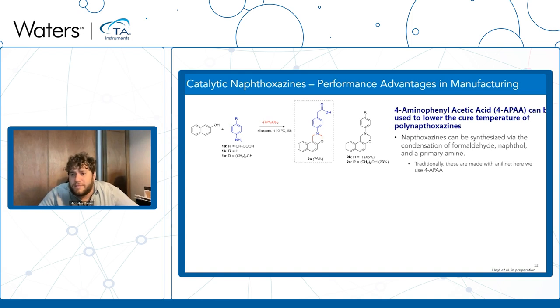And we can make robust materials. The problem with naphthoxazine resins today in their manufacture is that they often have to use really high cure temperatures that often lead to extra equipment costs and extra manufacturing costs and can lead to part defects because you're often operating at a high temperature. So within this world, it would be best if we could actually lower the cure temperature of these materials. And how we've proposed doing that is with this catalytic moiety that we can find from biomass.